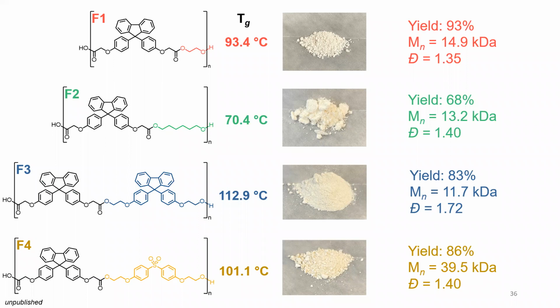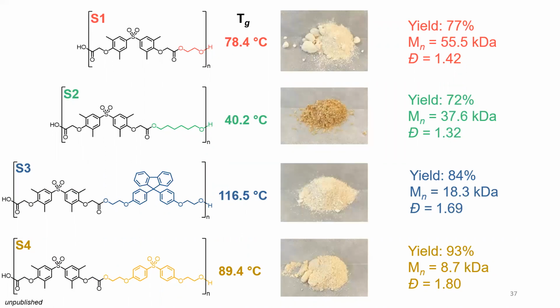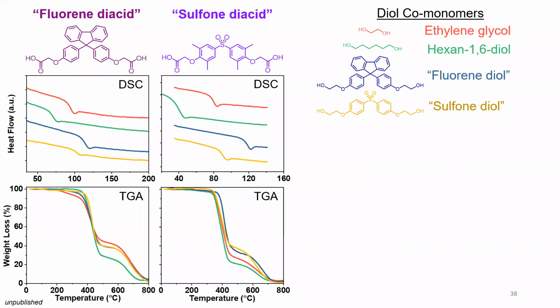And so we wanted to see if we can control the glass transition temperature, right? This is the temperature at which it transitions from a glass to a rubber. And so we could modulate that and then compare the diol versus the diacid, and then same thing with the sulfone. And then we could just reverse that and use the sulfone instead of the fluorene and get some polymer materials as well. So, like I said, we're right in the middle of looking at the degradation studies for these. So I'm going to hold until I finish that to share them with you.